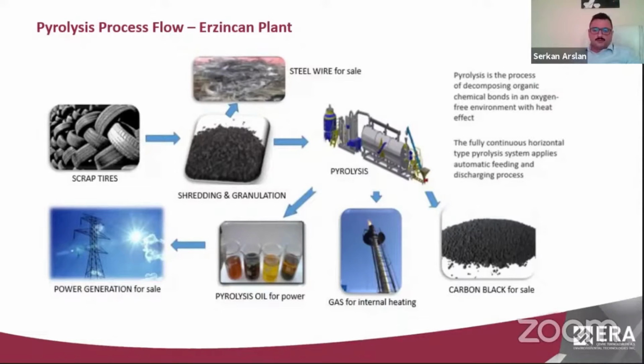The pyrolysis process, as you know, is decomposing organic chemical bonds in an oxygen-free environment with heat effect. We remove the oxygen with nitrogen to make an oxygen-free environment. Then, as you know, we heat the reactor, and because of the thermal decomposition, the organic part of the tires goes into the gas phase. Then the light oil and heavy oil are separated in the separation towers. Then they are condensed and turned into pyrolysis oil, tire pyrolysis oil. And in our system, we separate them first, but then we mix them together again.